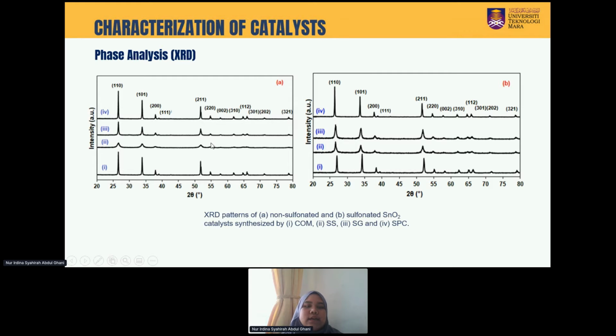That indicates it has the lowest crystallinity due to no heat applied during the synthesis reaction, no high temperature is used. The crystallinity increases when increasing the reaction temperature, 50 degrees Celsius for the sol gel method and 350 degrees Celsius for the SPC method, self-propagating combustion. So increasing the reaction temperature results in an increased crystal growth rate.